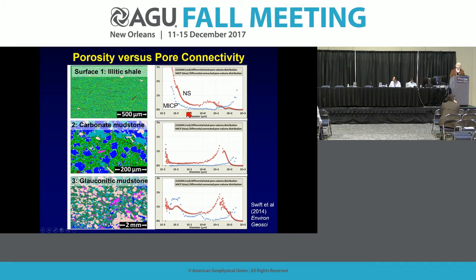The reds are from neutron scattering. Neutrons pass through the whole sample and see all the pores. The mercury porosimetry, of course, only sees those that are connected pores. And so you see that in this case of the illitic-rich material, we get a fairly similar map between the two techniques. Why should this be? Well, the pore throats, which is what mercury porosimetry accesses, and the pores themselves, which neutrons see, are roughly on the same order of magnitude in size and shape.